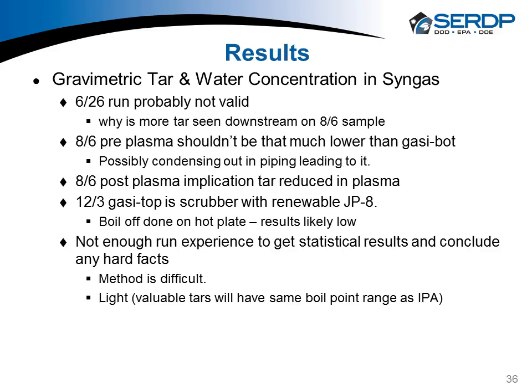Post-plasma, the fact that the gas and the liquid showed very little coming out, we were destroying it somehow. Same with the catalyst. Again, the gasifier top is running a scrubber with renewable JP8. We did a boil off on a hot plate because we couldn't use the standard TAR protocol rotary evaporator because the boil point of that is so high. So those results are likely a little bit low. And again, we didn't have enough experience to get statistical results and get some good hard facts. I mean, this method is difficult to run.